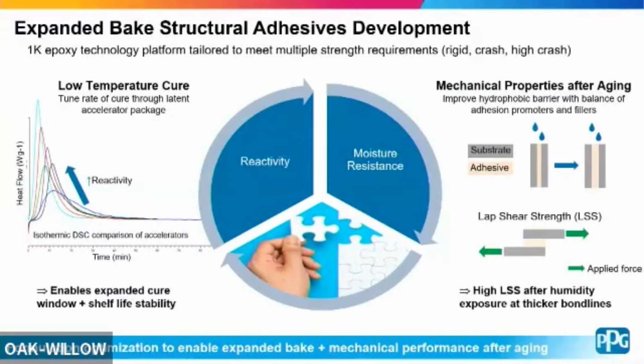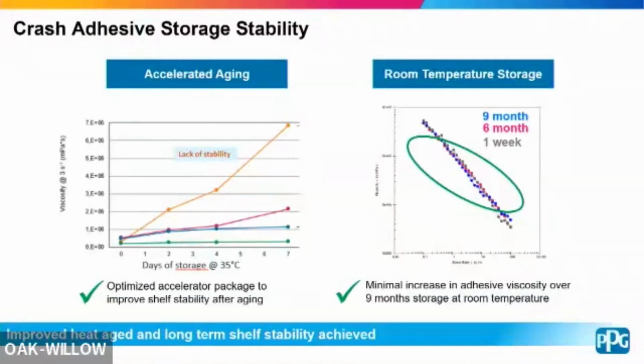So just showing with these two innovations, we were able to enable these different properties, and I'll just show some of the data that supports that. So this is our crash adhesive, just showing some of the storage stability that's been achieved. So you can see we have accelerated aging, so that's just tracking viscosity over days of storage at high temperature, in this case 35C. You can see with that orange curve, that's not what you want to see, where you're seeing a big viscosity climb pretty quickly at high temperature. And we were able to formulate around that to bring it down to more close to that green line, where you have a really good stable viscosity over time.